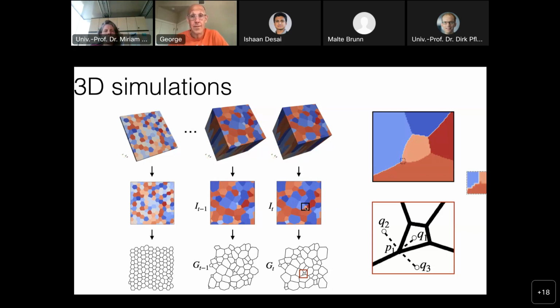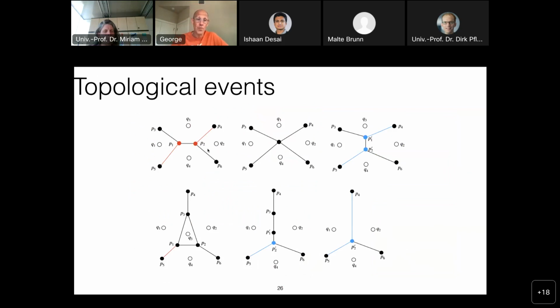And that's the very challenging part that we resolved approximately. I'm not going to discuss the solution because the details are complicated, but I'll give you the main idea. So this is a representation of the event. Imagine that there's one grain here, another grain here, another grain here, another grain here, and that's the interface or the face between two grains. As the simulation goes, this face will disappear. In the next step, the face disappears, and in fact, a new face appears between the different grains. Notice that grains Q3 and Q4 are neighbors because they share a common face, and Q1 and Q2 are not neighbors at the beginning of the simulation.